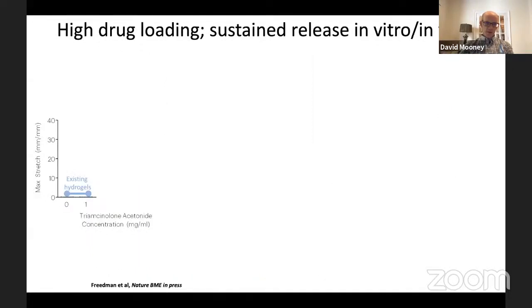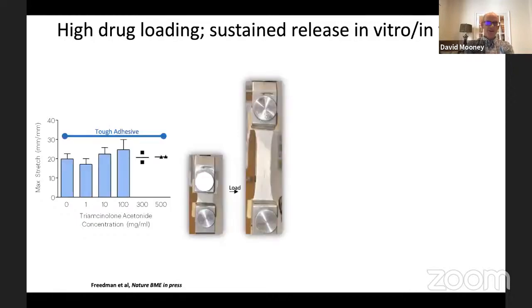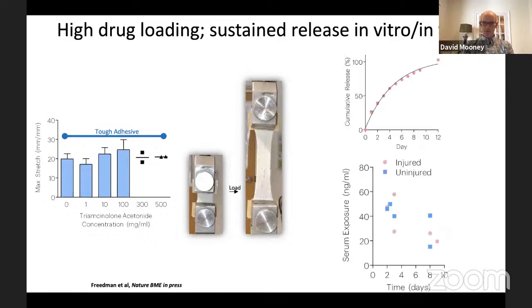Now, we can load these with drugs, and unlike existing hydrogels that tend to enable only a very low drug loading, here we can actually load up to 500 mg per mL of drug into these patches. So at this point in time, half of the mass of the system is drug, and about 5 to 10% of the mass is polymer. So we actually have a lot more drug than we have gel there, or at least polymer in the gel. This does not alter the really favorable mechanical properties, as you can see by their ability to be stretched.